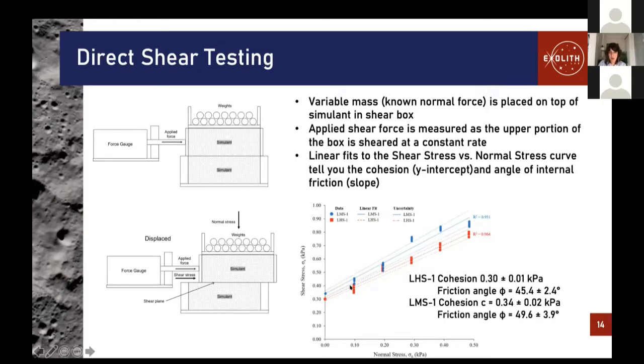And if you make a plot, depending on how much weight you put on top, for each normal stress and each corresponding shear stress that you need to displace that box, you'll get a linear looking curve, and you can fit a line to that. The slope will tell you the angle of internal friction of the simulant or the material, and the y-intercept will tell you the cohesion. And we've done this for our lunar simulants and actually almost all of our simulants at this point.